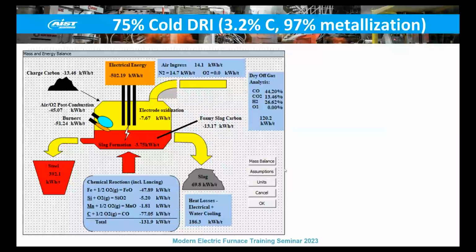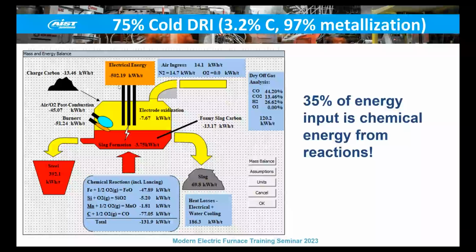Here's a model showing cold DRI with 97% metallization. This is a little higher, but in the end, the electrical energy on the previous example showing 10% pig and scrap was 450 kilowatt hours, but now you're looking at 502 kilowatt hours per ton. And in this case, only 35% of the input energy is chemical. I believe this was modeled using a slightly lower carbon content of a DRI pellet.